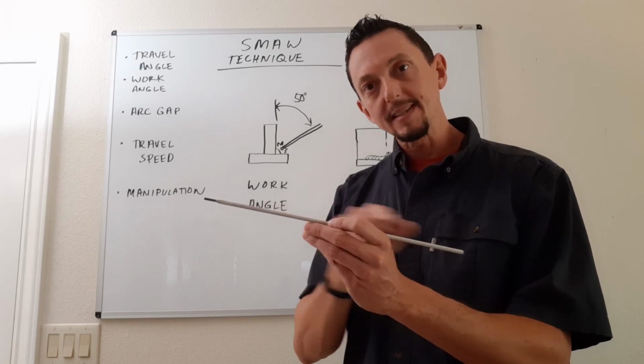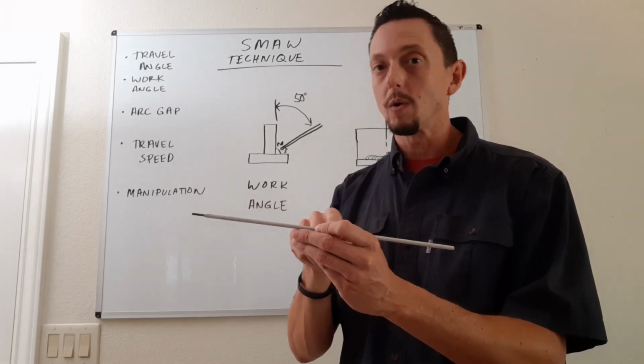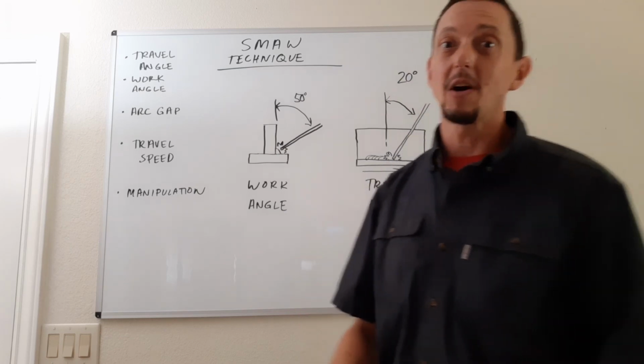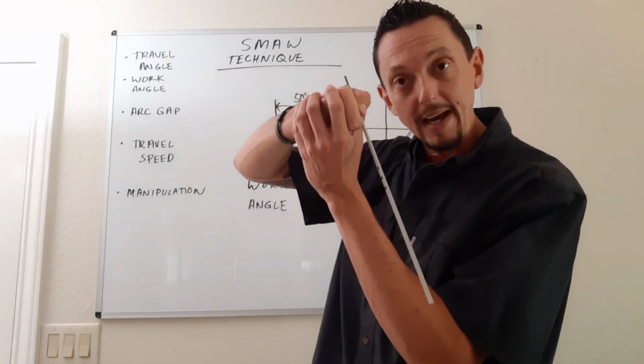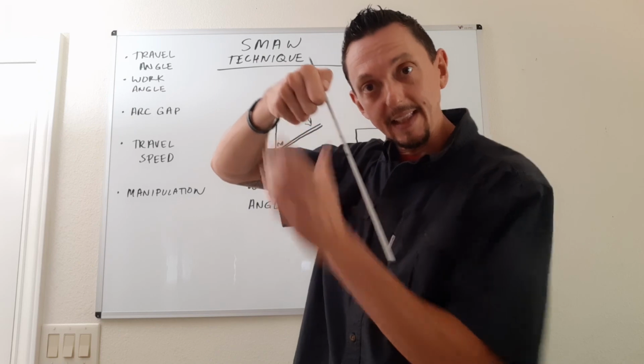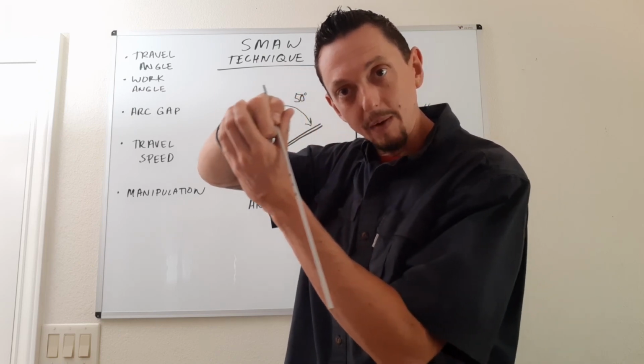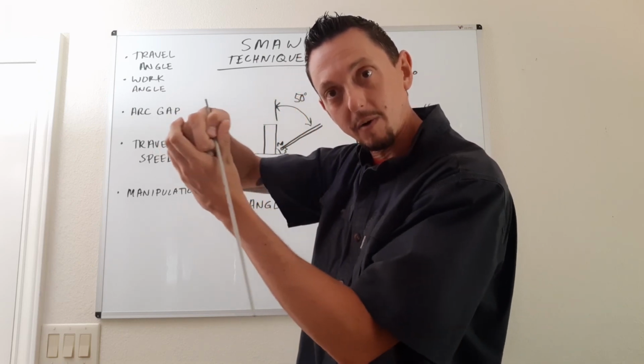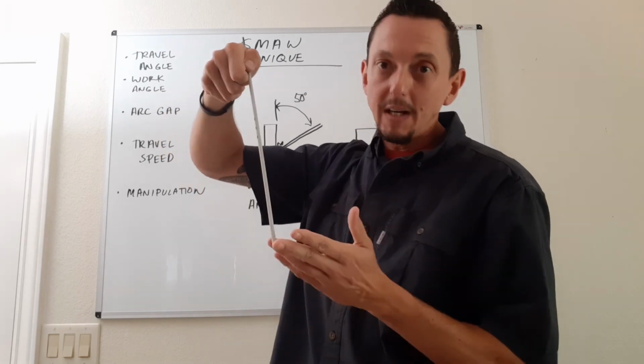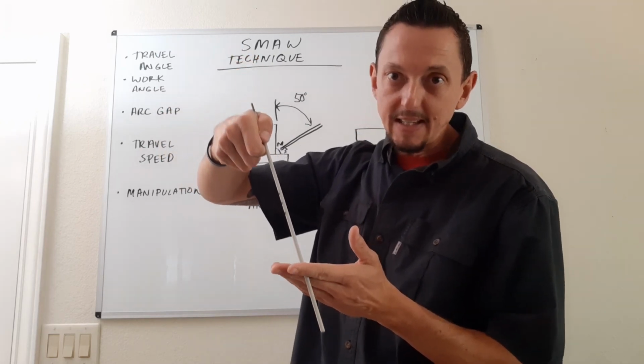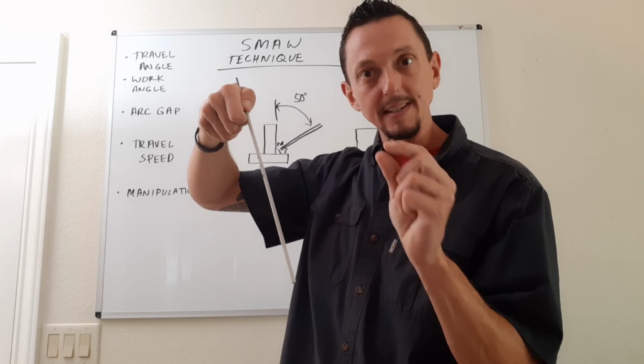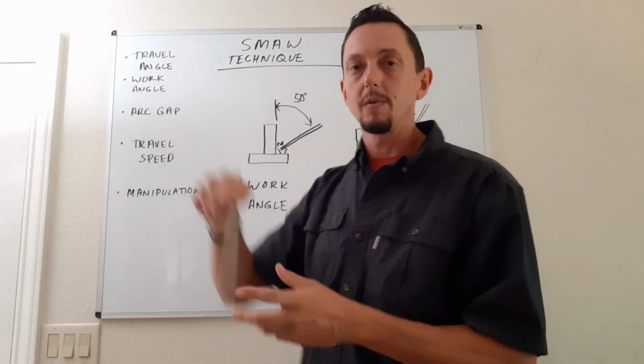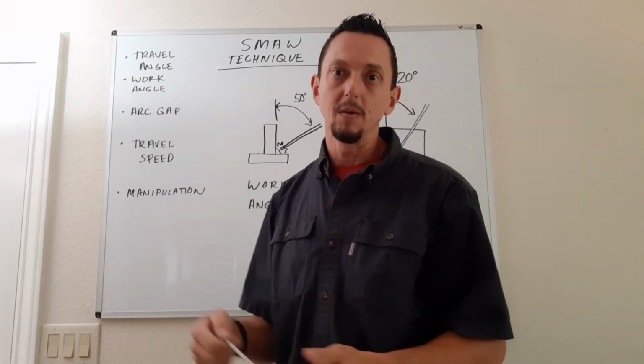This metal rod that's inside of here gets burned away as we're welding. So this is another thing that's hard. And I see a lot of new welders that, as they're welding, this thing is burning away. They're doing okay with their travel speed. They've got their angles okay. Well, now, they have to think about feeding in this electrode and keeping that arc spacing nice and tight as they're going through, as they're getting to the end of the weld, okay?